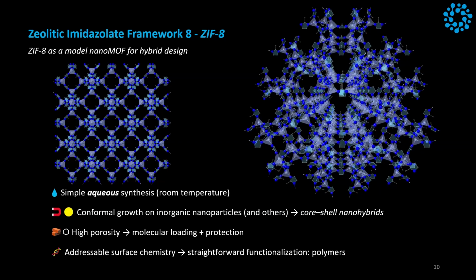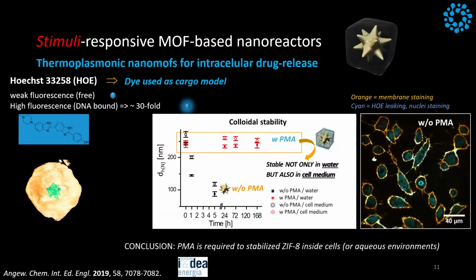And because we know that for 30, 40 years, we use CTAB for growing nanoparticles, if we use CTAB-coated nanoparticles, we can grow ZIF-8 on top of it. Okay? Any nanoparticle, as long as we put CTAB on top of it, we can grow the ZIF-8. There are papers in JACS and so on explaining why this happens with the micelle concentration of CTAB and the kind of structures that you do, but you end up with beautiful nanoparticles with this. So this is the first study that we do.